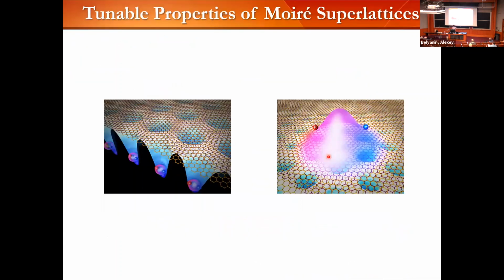So now, another way for us to further convince ourselves that this has anything to do with the Moiré potential is to start tuning it, right? What we find is that the lifetime, meaning how long the interlayer exciton lives, or whether or not they can move around, depends on the twist angle. When the twist angle is small and the Moiré supercell size is large, I tend to localize these carriers. But when I make the unit cell maybe 2 to 3 nanometers, they can actually smooth out the energy landscape and start moving around.